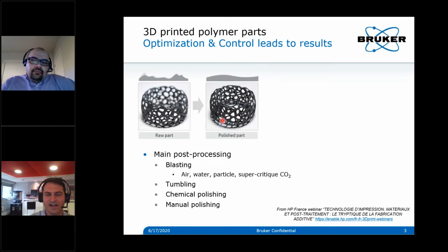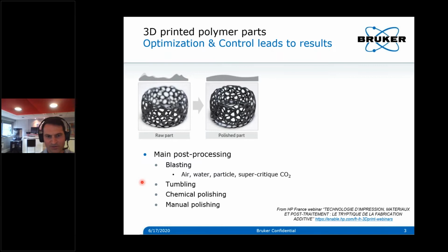It can be as simple as air blasting, just to remove non-anchored or tiny particles from polymers that are not very adherent. It can be blasting with water or some beads, as well as using a bit of chemistry with supercritical carbon dioxide. Or for relatively stiff polymer parts, like PET ones, you can use regular mechanical tumbling finishing with abrasive cones, and having the right time will help to smooth out all the angles. So tumbling is really for the outer surface. Blasting, for instance, helps to reach some specific locations. However, both of them are really limited whenever the parts become complex.